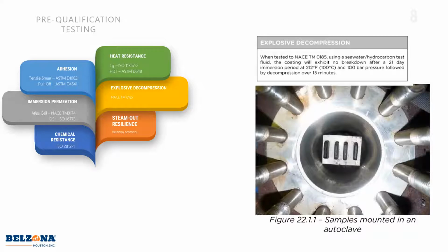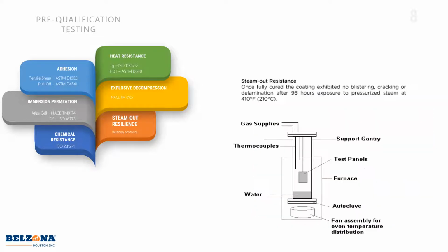And we do this with a lot of gases, hydrocarbon gases, and seawater, just to make sure that it can handle that. And then finally, we know that to inspect a coating after it's been in service, you have to put it through a cleaning and steam out regimen. So we do steam out testing to make sure it can handle that as well. So we make sure that it's going to handle the service, it's going to handle the cleaning, and then you can put it back in service once it's been inspected.